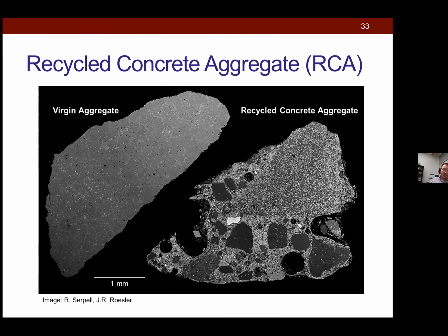Okay, last one I want to talk about real quick is recycled concrete. Recycled concrete's interesting because now you have a lot of variability in the composition. So you kind of have your old aggregates, your old mortar. You can have these old ITZs. If the material was undergoing some sort of durability issue, now you can have some latent ASR. Maybe you have some high chloride contents, high sulfate contents. Localized microcracking. Maybe you got microcracking during the crushing operation.